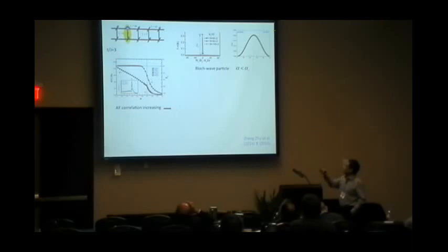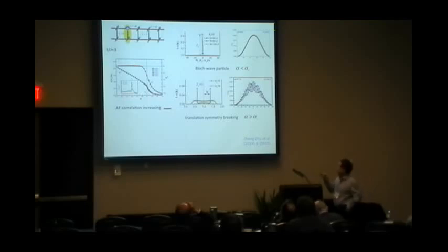This is a numerical simulation done by two of my former students. It turns out if alpha is some control parameter where the correlation is very short, you find that the hole will be just like a quasi-particle with a well defined momentum, and the real space distribution with open boundary is a smooth curve. But once you increase the antiferromagnetic correlation by tuning the parameter, such that the correlation is long, then you find a critical point, where this is the ground state energy, and then there's a dramatic change of the hole motion. You see, the momentum distribution is now reconstructed. There's a split, a single momentum, not two, with some broad feature. And then in the real space profile, a charge modulation comes out.